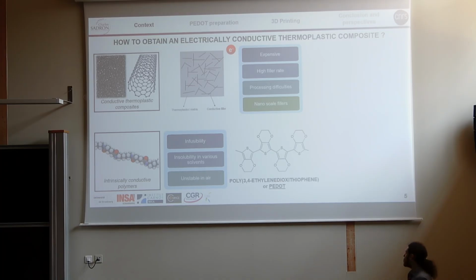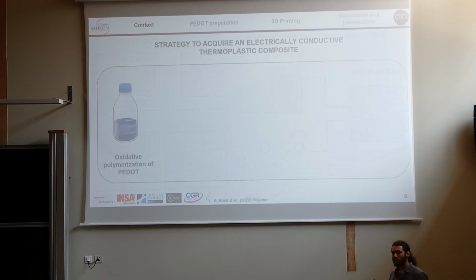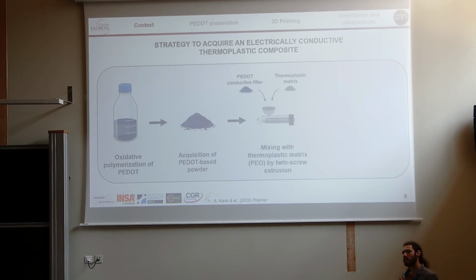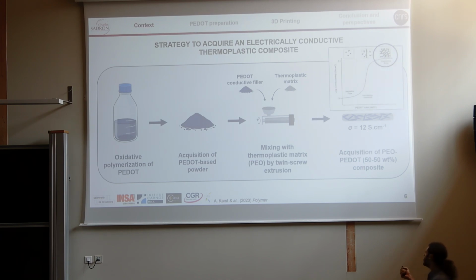By combining those two methods, we created a new one at the lab, and it consists in the inclusion of fillers of conducting polymer into a thermoplastic matrix. Some work has already been conducted on this strategy by a former PhD student who first created a PEDOT powder by oxidative polymerization. Then she mixed this powder by twin screw extrusion inside a PEO thermoplastic matrix to obtain a conductive composite which can reach up to 12 Siemens per centimeter of conductivity. As you can see here, there's still a very high filler ratio.